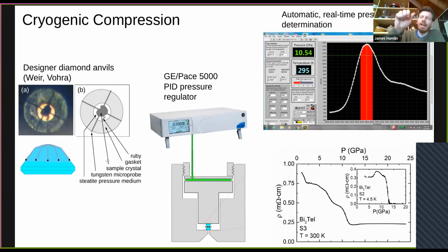Rather than a simple knob on a gas bottle, we use this PACE 5000 pressure regulator. This is basically a computer-controlled pressure regulator that lets us program in a sweep so we can very gradually sweep the pressure even at low temperature. This is all coupled to a system that does automatic real-time pressure determination by measuring the ruby fluorescence and then fitting a peak function to the peak. It takes into account the temperature correction to the ruby signal as well.